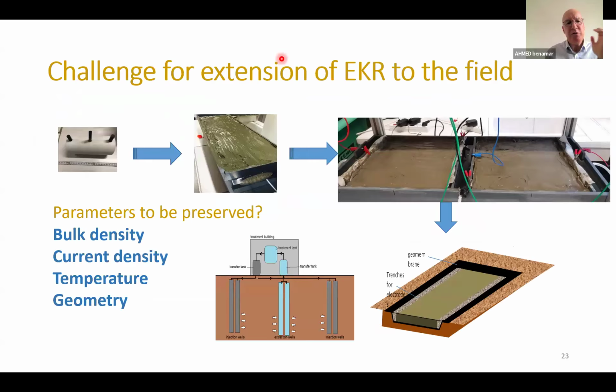And after that, we used experiments of many sizes to start investigating the upscaling of this process in order to use it in the field. But we are still investigating this because the theory of upscaling is different from other fields like hydraulics. So we started by using the bulk density as a parameter to be preserved from one scale to another, as well as current density, temperature, and geometry. So when we increase the volume of treated sediment, the temperature rises and the process was inhibited.